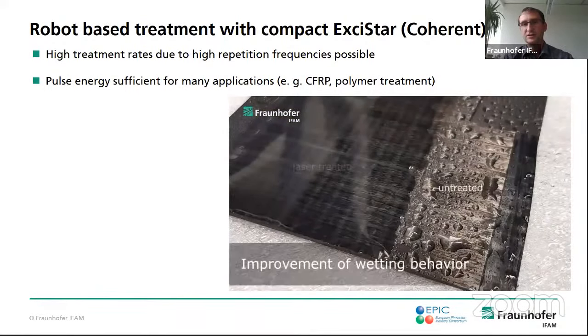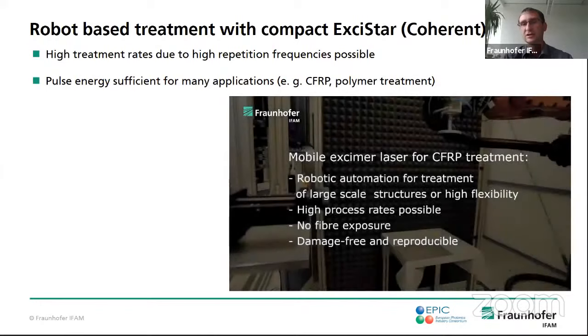The effect can be seen here. On the left side, you can see the laser treated area, which shows a very good wetting behavior. On the right side, the untreated surface. And that means in total, you can use UV excimer lasers for robotic automation. You can use it for high process rates, and you can treat CFRP parts without fiber exposure and so in a damage-free way.